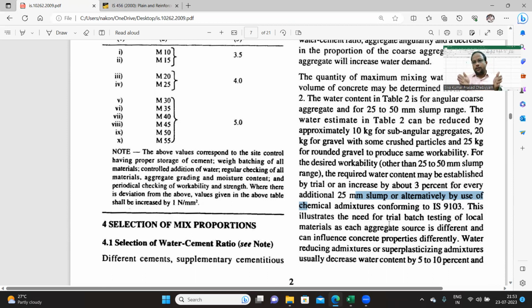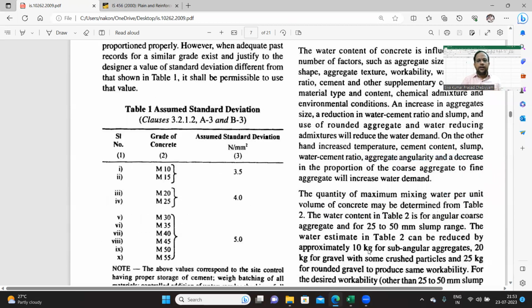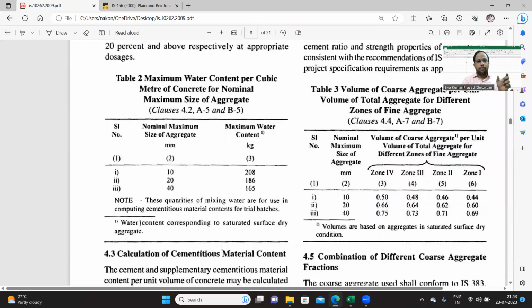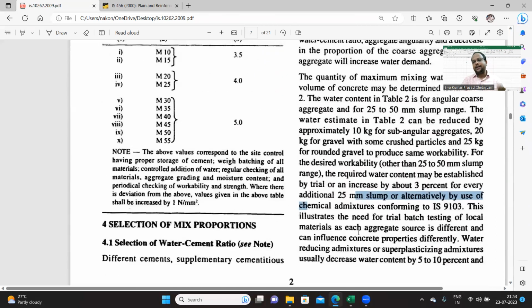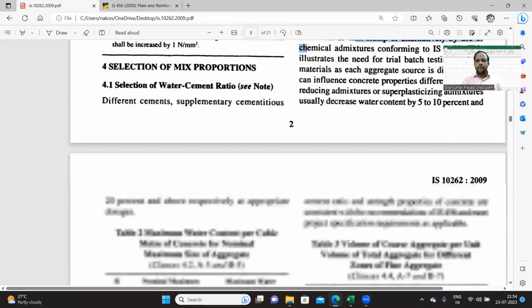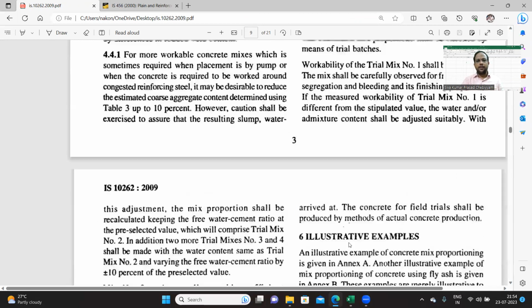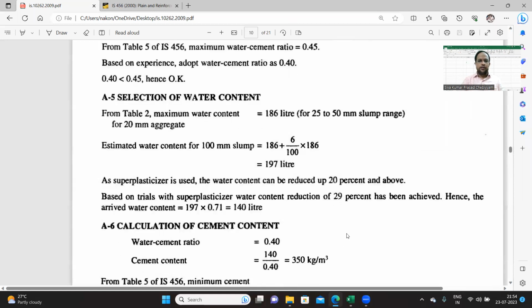That means you have to go for 6%. So table 2 is for a slump value of 25 to 50 mm. For any additional 25 mm slump, you should increase the water content by 3%. Let us see the illustration also. For table 2, for 20 mm aggregate, this value is only for 25 to 50 mm slump.